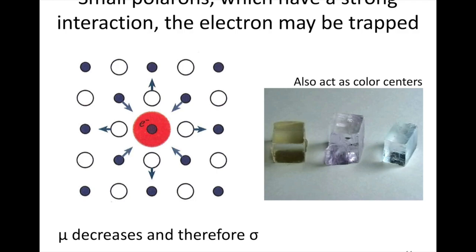And so if we think about this, this ionic trap that can trap an electron decreases the oxidation state if we're talking about a cation. So if we're talking about a metal ion, a positively charged species, if we trap an electron, that's the equivalent of decreasing the oxidation state. Right? I go from, for example, iron 3+ to 2+ when I trap that extra electron.